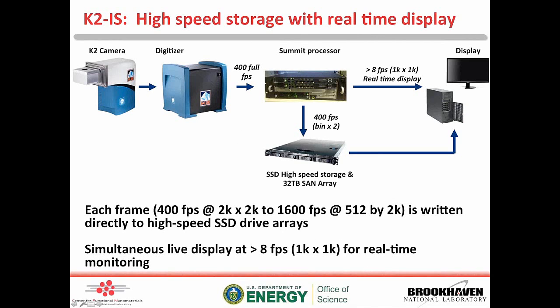The idea here is that you take from the camera the high frame rates, and you basically incorporate a supercomputer so that you can read them at very fast frame rates. This thing will take pictures at 400 frames per second with 2K by 2K, so really high resolution images. If you want, you can actually run it at 1600 frames a second, where you just stream off the top of the camera and get 512 by 2K. And this is then basically written directly to an array of solid-state drives. We can store up to 32 terabytes in solid-state memory.